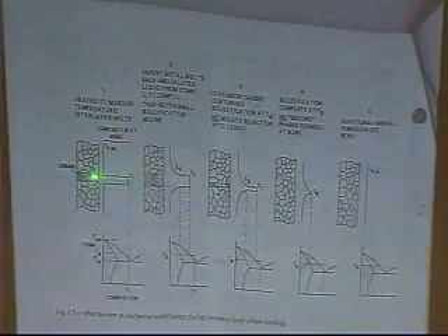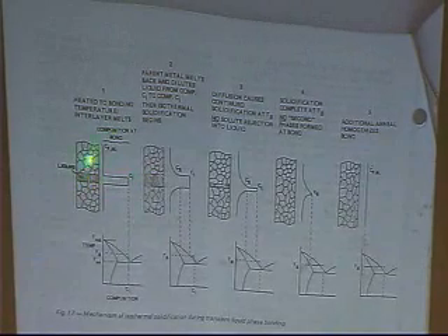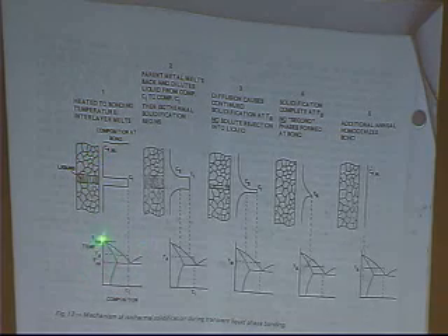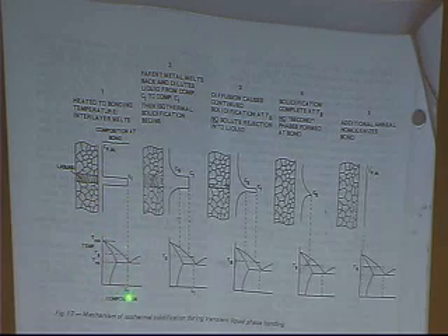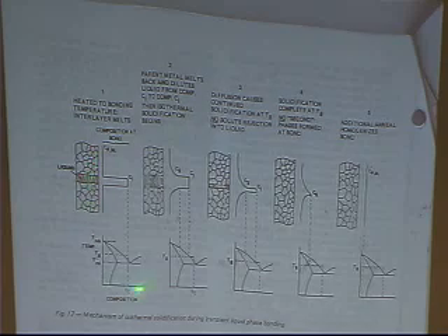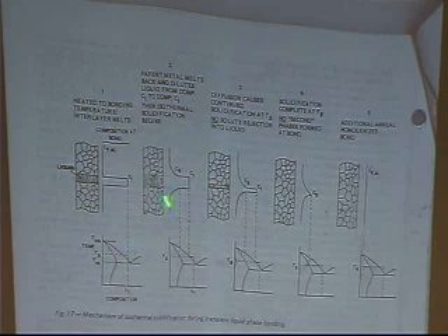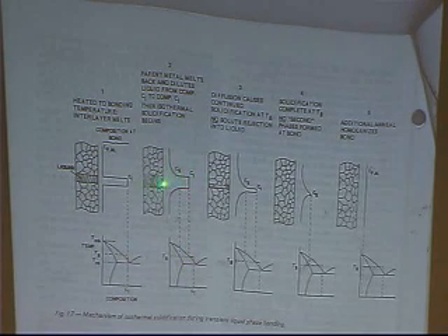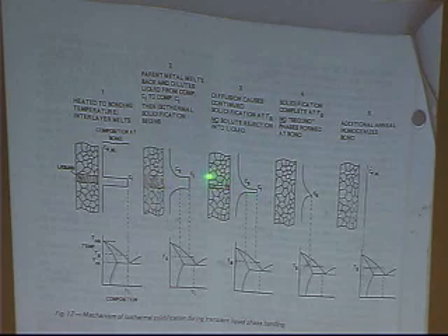I have a liquid between two solids. The composition is very rich in boron in the liquid and no boron in the solids. This is the phase diagram. No boron, everything solid. I add boron, I have this type of phase diagram with this amount of boron, C1. And so this is liquid, this is solid at this temperature. As I heat it, I actually will dissolve some of the parent metal, and the bond will get thicker, and my center composition will be the same composition as what sits on this line, and I'll start to diffuse the boron away. If I hold it there for a long period of time, that thick liquid region, as the boron diffuses away, will get thinner and thinner.